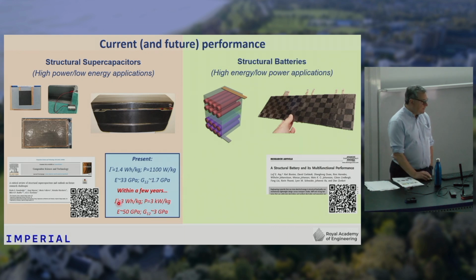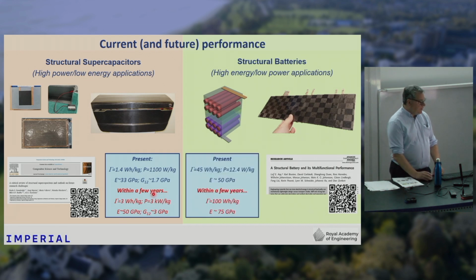This is where we expect to get to over the next few years, pushing up the power and energy density, but our material also has mechanical properties. So this is the Young's modulus and shear modulus of our material, and it's getting towards what you get for a conventional composite. The battery technology has much higher energy density, so they're currently at 45 watt-hours per kilogram.